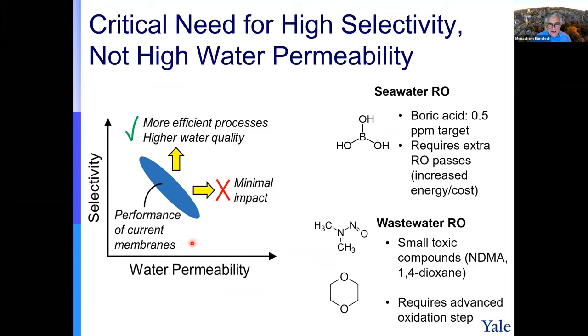In membrane science, we typically present the selectivity of membranes as water-salt selectivity: how much better you pass water than salt. We need high selectivity, and this is the water permeability. Experimental data for membranes fall roughly in this range, more like a trade-off. If you want high selectivity, you will drop the water permeability. And what I showed you in the first part, the earlier topic I just finished, is that if you just improve the water permeability, there will be minimal impact on energy efficiency.